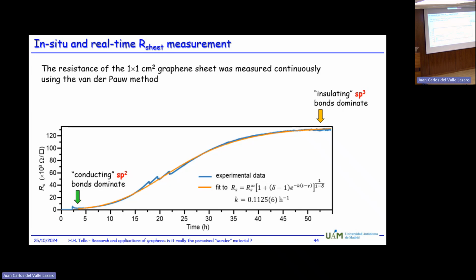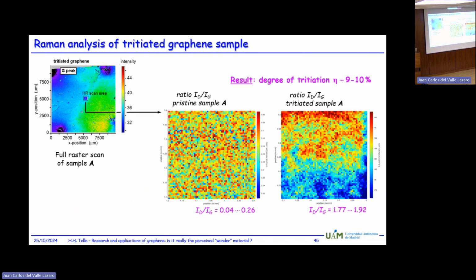Now, after the experiment, at this point, we have taken the sample out and put it into our Raman microscope. And here are a few examples of the measurements of these samples after the exposure to tritium. And here is the complete picture of the 10 by 10 millimeter sample. And you see actually here in the corner, well, this corner is actually out because it was a little bit turned. You see black parts, and those are actually the points where the electrical contacts were at the sample, and basically you destroyed in the way the graphene.